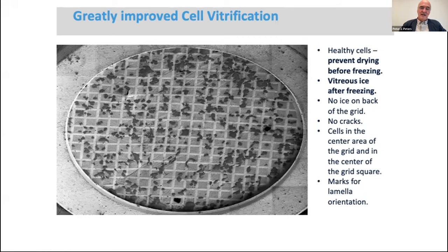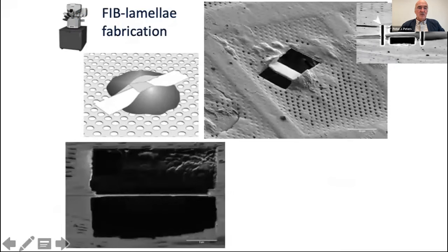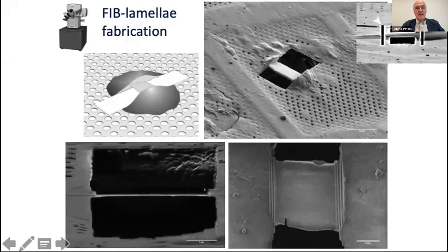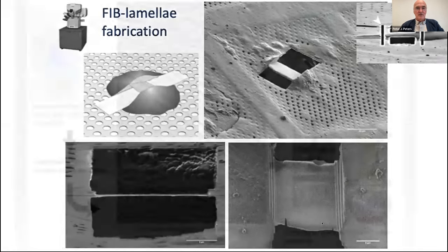So making the lamellae is, as most of you probably know, also well known in the material science community. In this case, imagine you have a cell, but you can also imagine cream or a kind of polymer that is on a grid. You make thin lamellae, and that is done via a procedure that was a bit modified by the Bram Koster group in Leiden, where you have, to avoid that these will break easily, some extra security gaps here. And then once you have these lamellae, you can get them at the moment on average, I think 130 to 160 nanometer. And they are in this case, I think, 2 by 2 micrometer. But currently, you can make with new machines from Thermo Fisher overnight, I was told, 130 of those lamellae automatically. You don't need anybody taking care of those anymore.